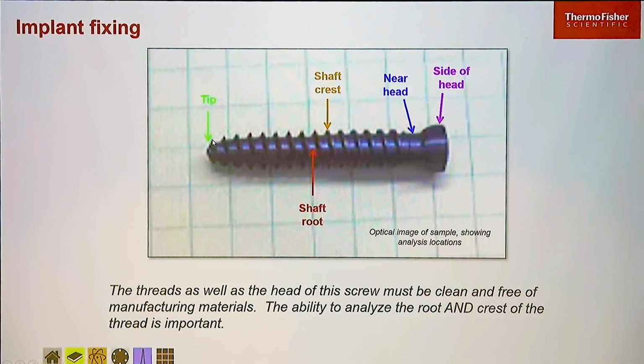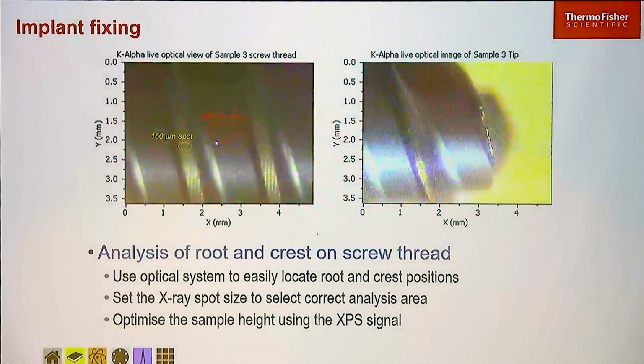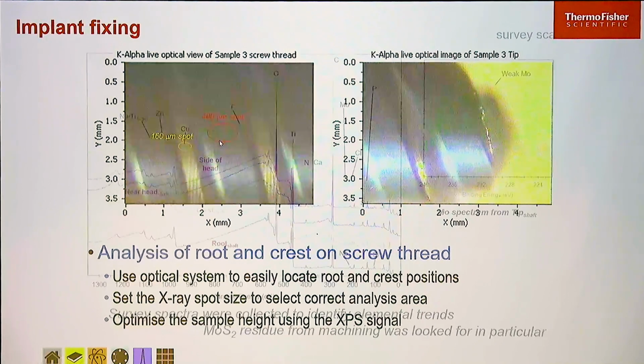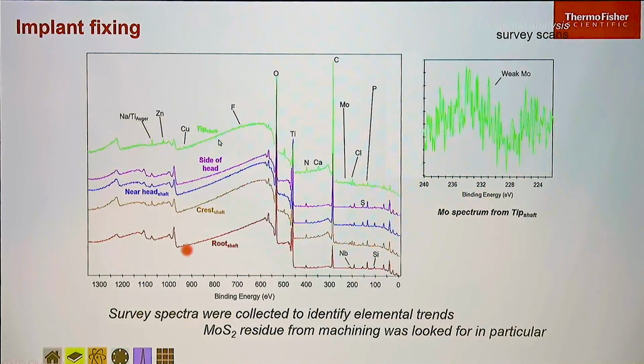And this is the screw here. So we've got the tip. Then the root is the section between the threads, and the crest is the top of the thread. And then obviously up at the head here is the fixing where the part would be added on at the end. And so what we want to do is use XPS to analyze different spots on the material to check and see whether there's any residues from the production process there left on the surface. So we've got the root, the crest, and then near the head, on the side of the head, and the tip at the opposite end to the head.